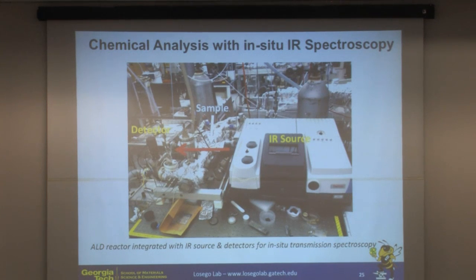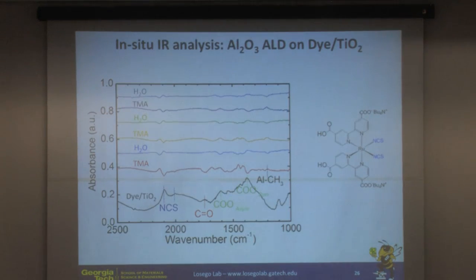Okay, we've also looked a little bit at trying to analyze the chemistry that's occurring in situ. So this was a system set up at NC State where we had an actual in situ FTIR with our ALD reactor. And so we were doing in situ IR spectroscopy while we were doing ALD deposition. We could look at each half cycle, so each exposure of our precursor, we could see what was occurring in our reaction. So these are the spectra that we collected as we dosed the alumina precursor, the aluminum precursor, then the water, aluminum, water, et cetera, for three cycles.